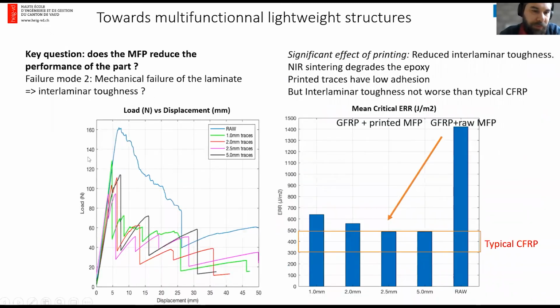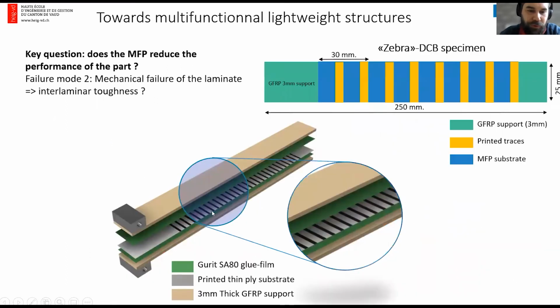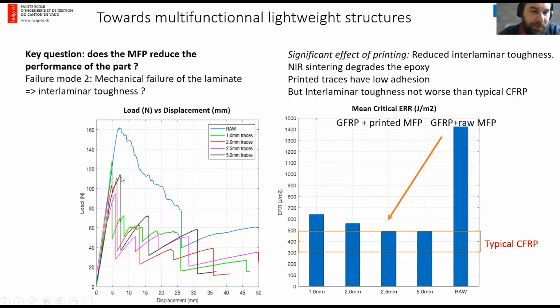So here you have the load displacement profile during the DCB test. Here you have the blue curve, which is the raw specimens. The raw specimens are not just GFRP; these are GFRP plus one layer of multifunctional ply like this, but without printing. So it's just the substrate itself. For printed traces, we have these different curves below, and we can see that printing on these multifunctional plies actually decreases quite a bit the load capacity of the DCB specimen, which is linked to the reduction of the fracture toughness.